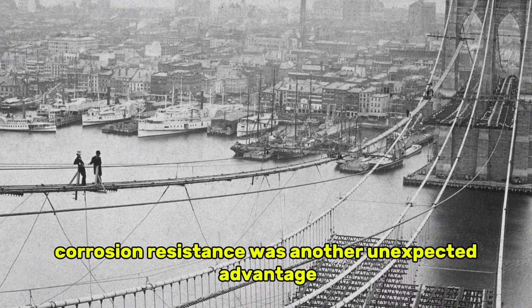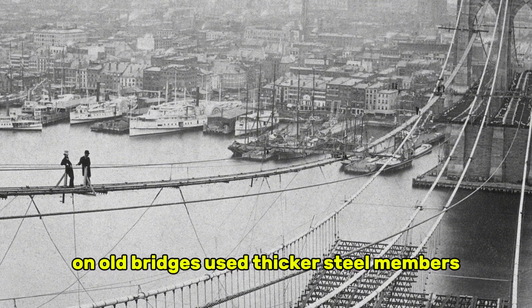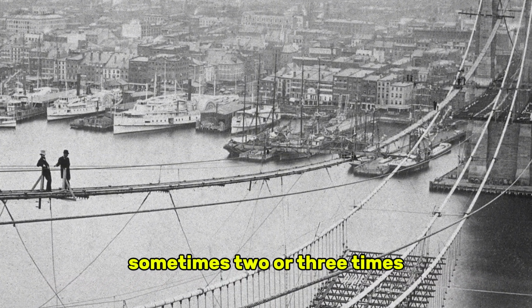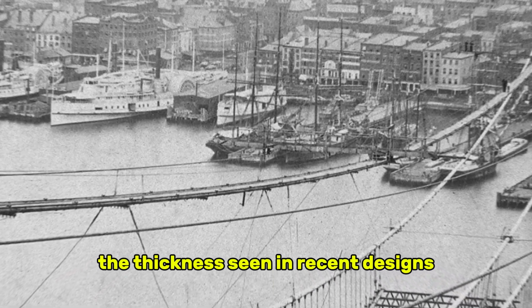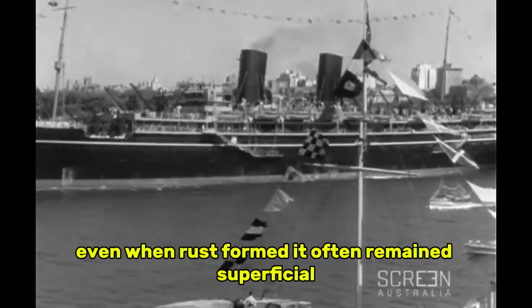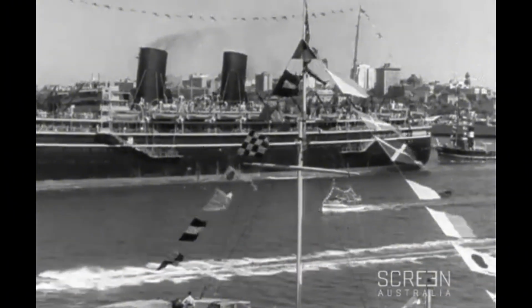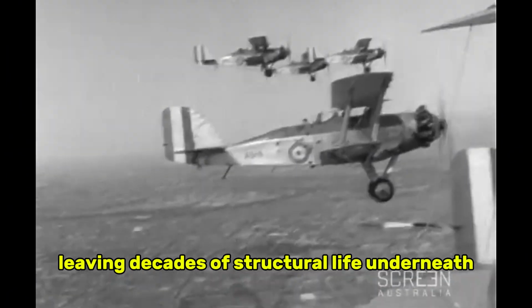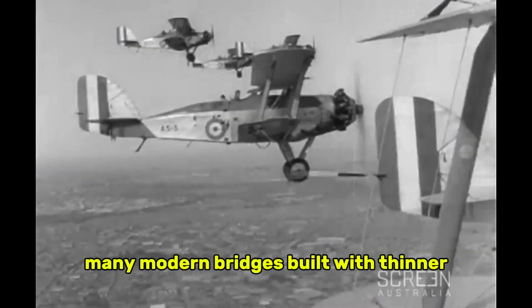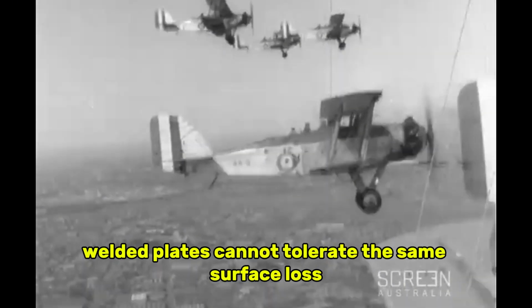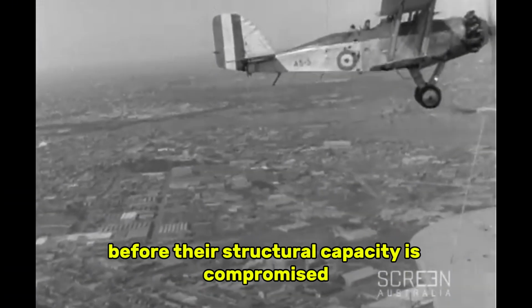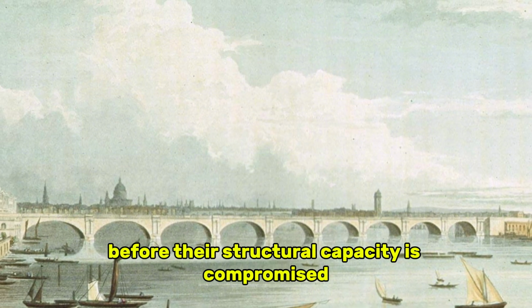Corrosion resistance was another unexpected advantage. Old bridges used thicker steel members, sometimes 2 or 3 times the thickness seen in recent designs. Even when rust formed, it often remained superficial, leaving decades of structural life underneath. Many modern bridges, built with thinner welded plates, cannot tolerate the same surface loss before their structural capacity is compromised.